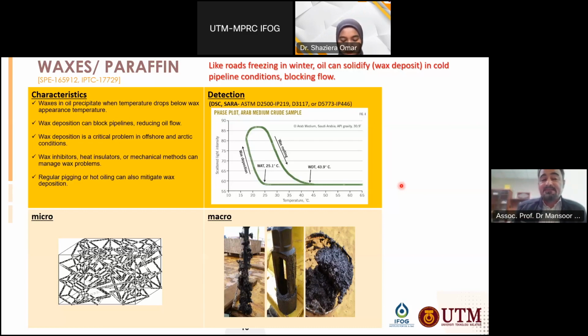like clogging pipelines. Wax disappearance temperature is the temperature at which the solid wax in the oil begins to dissolve back into the oil. So when the temperature of the oil rises above the WDT, the wax starts to melt and flow again with the oil. It's typically higher than WAT because of hysteresis, a phenomenon where the dissolution process requires more energy than the crystallization process. So here it's important to know these parameters to design appropriate strategies to manage the wax problem in oil production. For example, heating the oil to a temperature above WDT can help to manage wax.